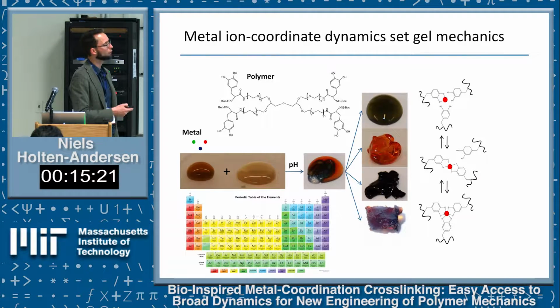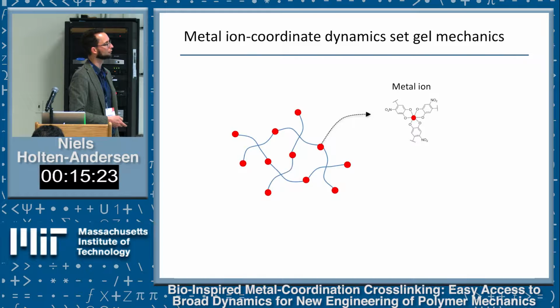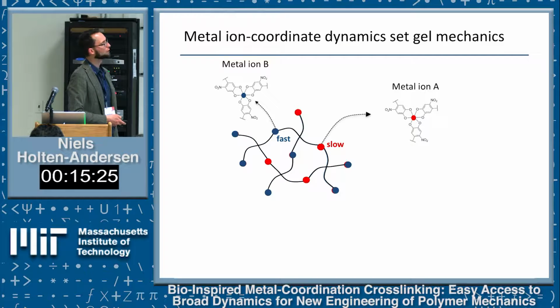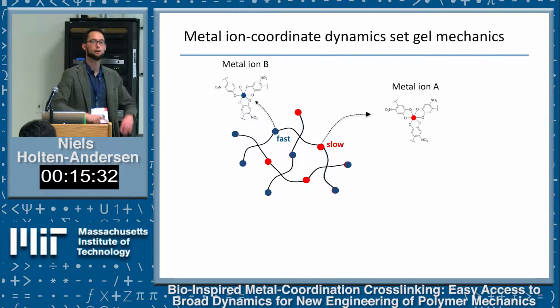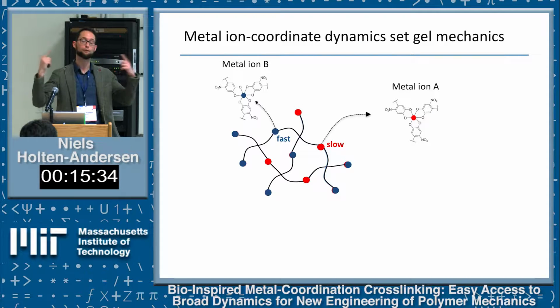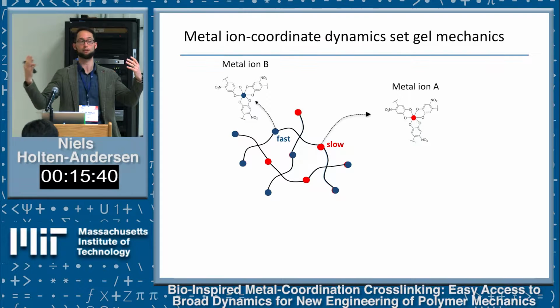It's all about where you are in the stability regime of the crosslink. So one of the first things we did was play this simple trick where we don't just add one metal ion to the network, but we actually add two different metal ions. If you pick two different metal ions that give you two different stabilities of crosslinks, you get both a fluid-like dissipative mechanism and a much slower, more solid-like dissipative mechanism.